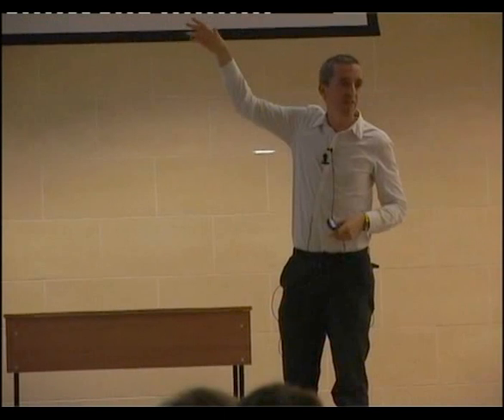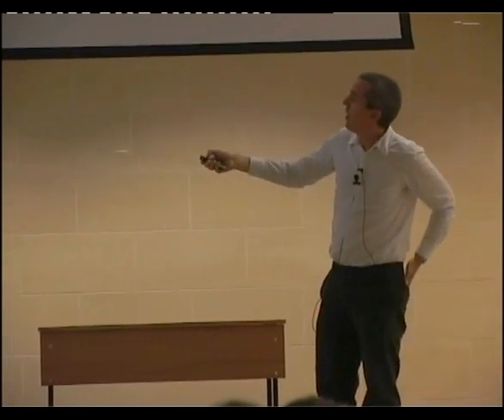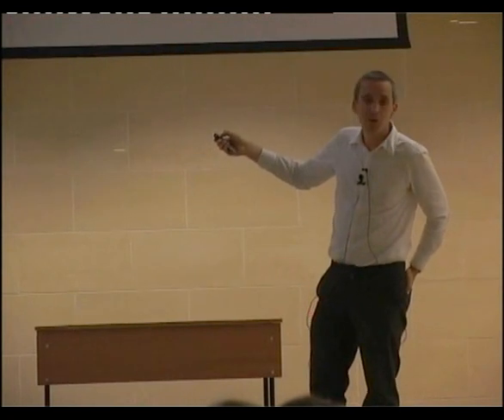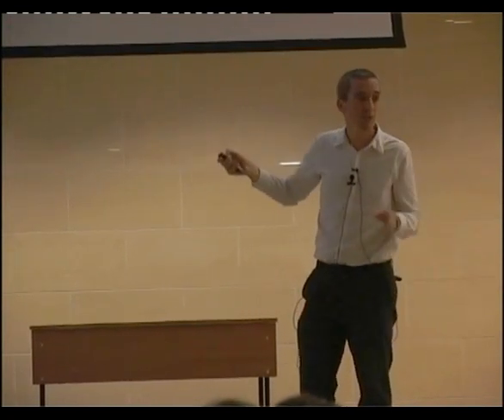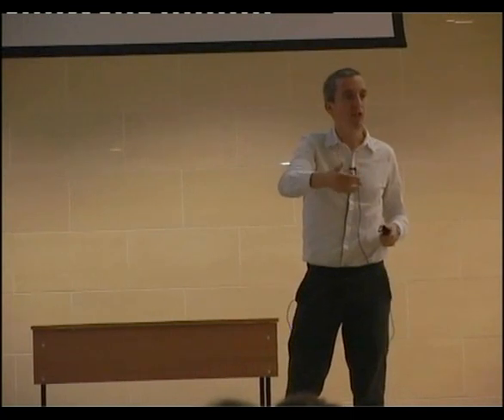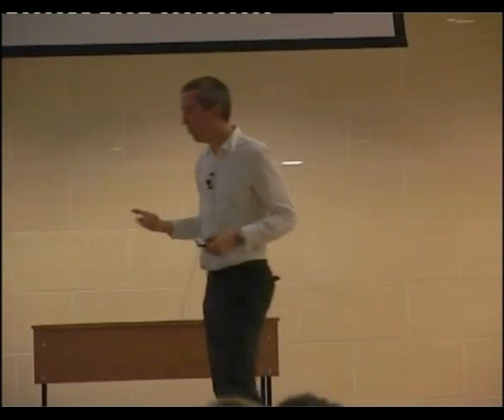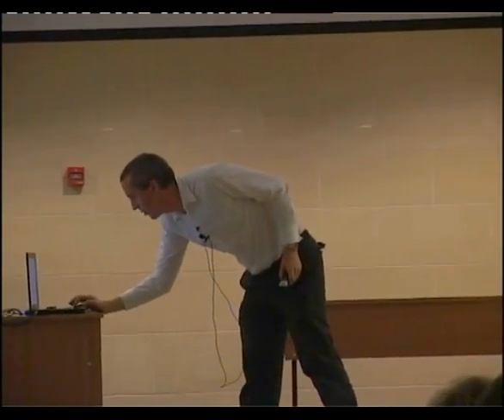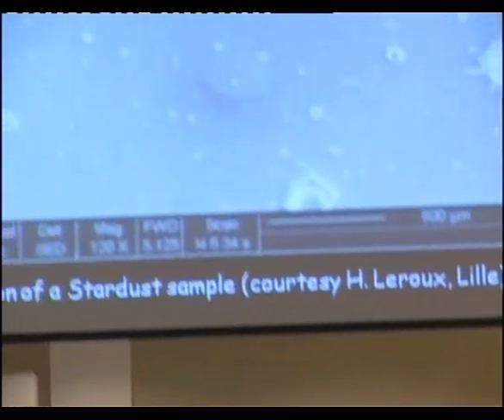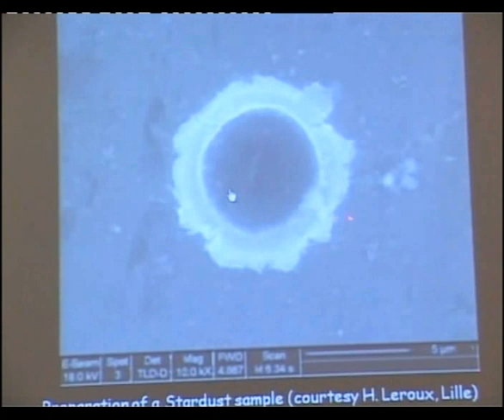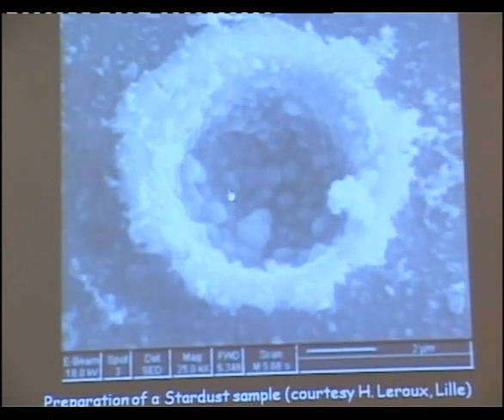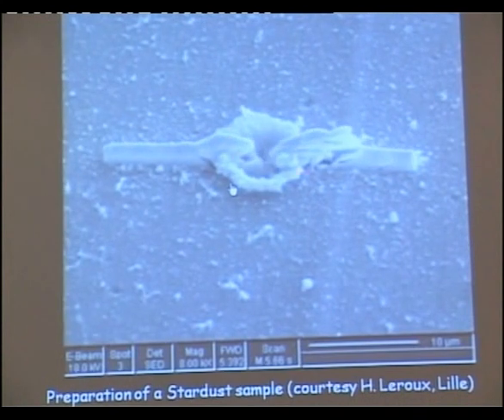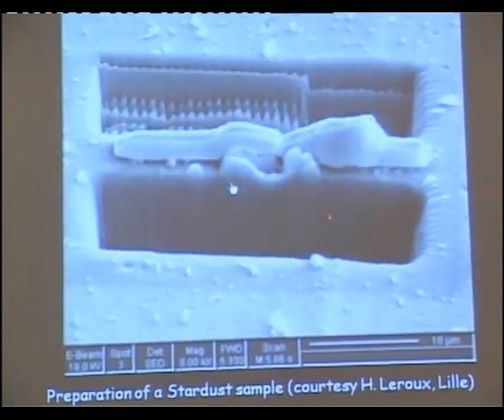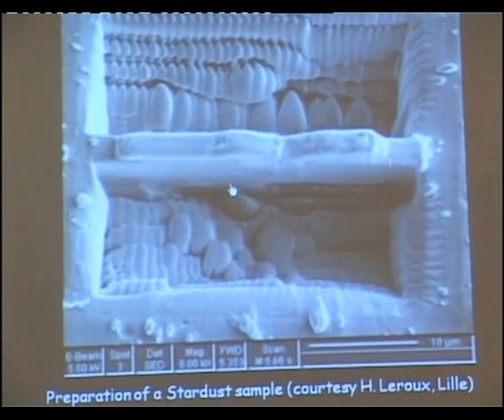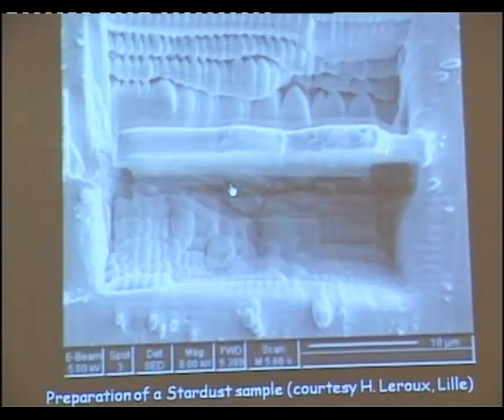I'll show you this very briefly. That's a movie provided to me by Hugues Leroux from the University of Lille, showing how they prepare a cross-section for TEM with the FIB. It's a completely different sample, but basically, these are SEM pictures. You magnify, you demagnify, and then you locate the sample area that you want to prepare. The first step is that they deposit a platinum strap on the sample, and then they dig into the sample, thin it, and then cut here, here, and here.